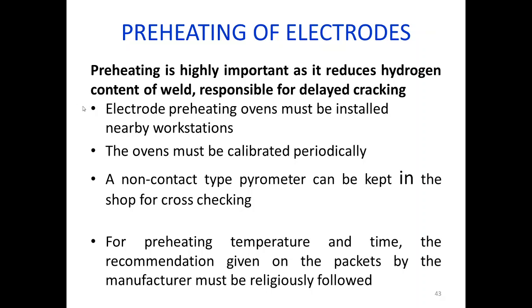Preheating, already we discussed preheating of electrodes. Preheating is highly important as it reduces the hydrogen content of the weld, which is responsible for delayed cracking. Not only is it a healthy environment, it also gives more strength to the welding bead and joint by reducing hydrogen content. If the electrode has hydrogen, what will happen after carrying out the welding activity? There are chances of cracking over the welding joint. So we have to go with preheating of electrodes religiously.